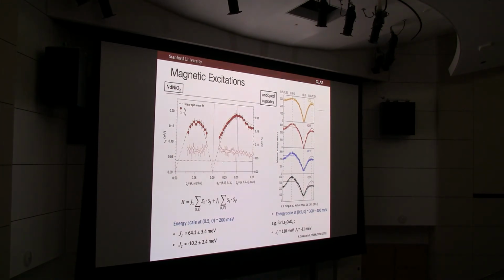If you take that data and just parameterize this by a simple near neighbor and next nearest neighbor spin model, you can pull out the exchange interactions that are, for comparison, what you might find in the cuprates. So the overall statement is that you have a pretty large magnetic excitation spectrum bandwidth that is of order 50 to 70% of that in the undoped cuprates as a scale. Here are some representative examples.